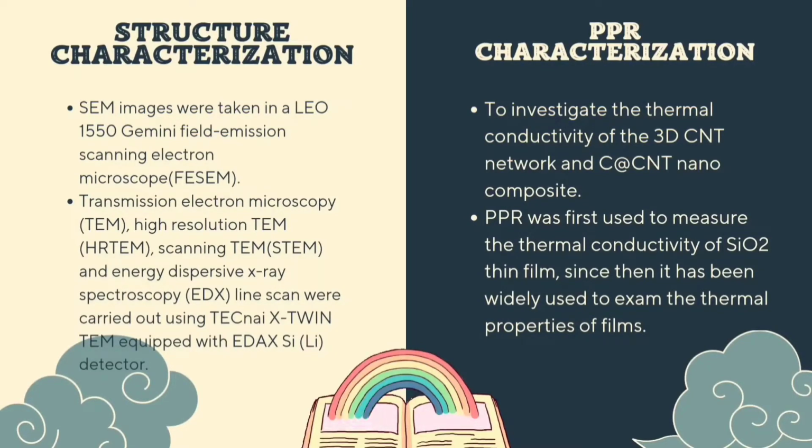The sample is first excited by the Nd:YAG laser pulse at a repetition rate of 10 Hz with a 3 mm spot size, pulse energy 30.3 mJ, and 7 nanosecond pulse width. This causes a fast rise in the surface temperature, followed by a relaxation. A 1 mW continuous probe beam with a spot size of about 20 micrometers is focused on the center of the pump beam to monitor the changes in light reflection from the metal surface.